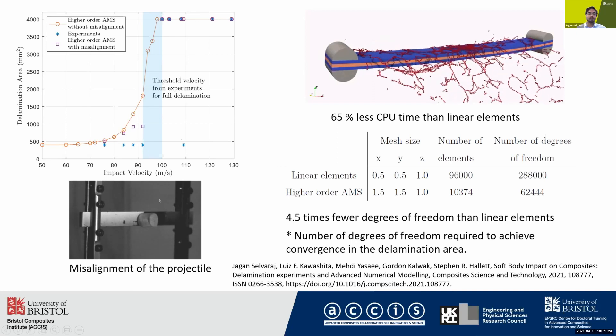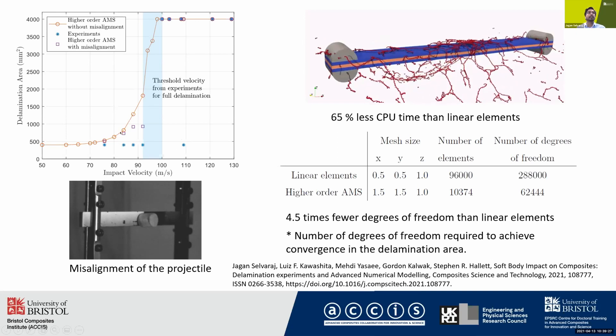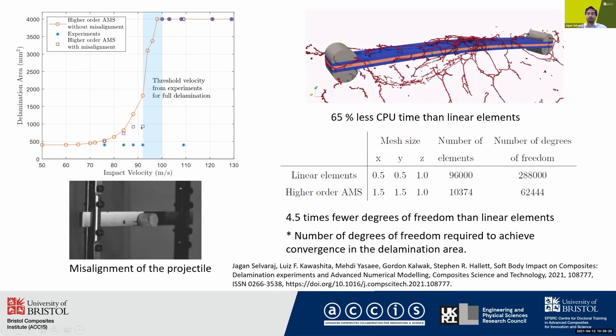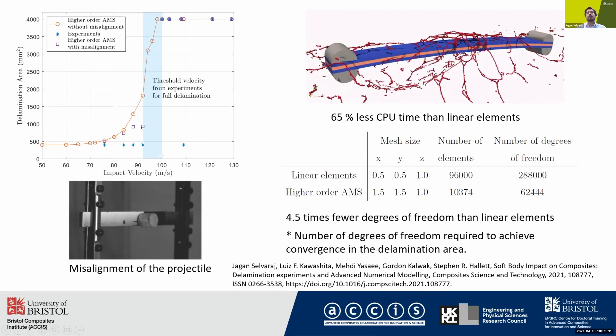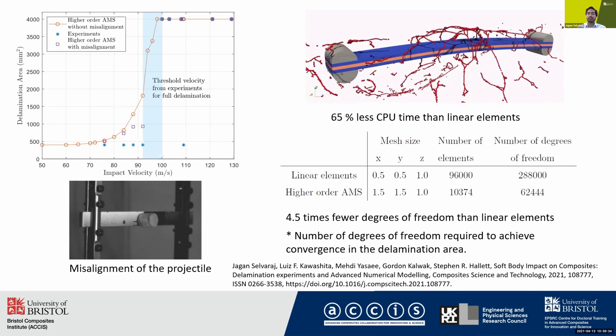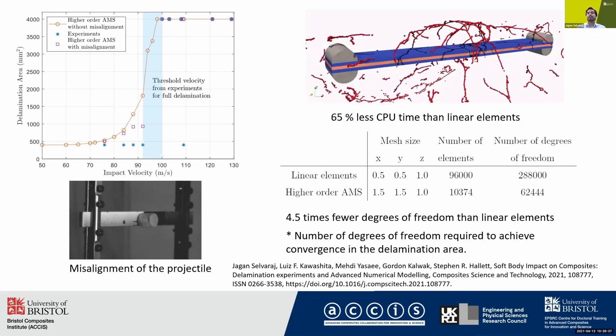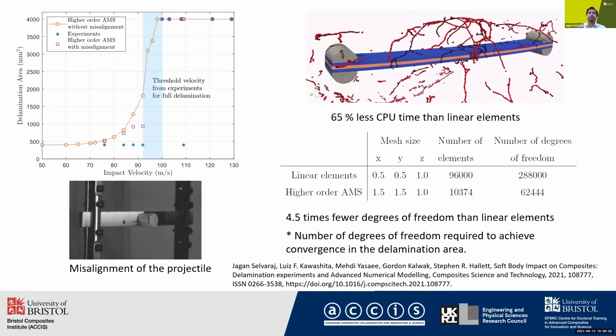Also, the experimentally observed behaviors such as the effect of misalignment in the delamination were also captured. In summary, using this method, we obtained a 65% reduction in computation cost by using four-and-a-half times fewer degrees of freedom. This work is published in Composite Science and Technology recently.